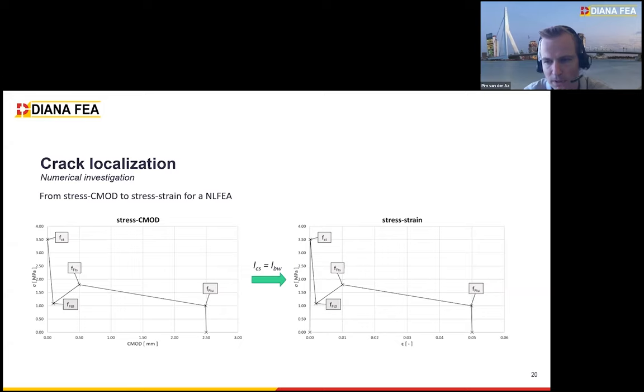And normally, as Professor De Prisco explained in the previous presentation, this is based on what your estimated crack spacing is. Your cracked zone, for example, that was the Y. However, this is for analytical models, and we are now looking at a finite element model. Because what you're actually doing in an analytical model is that you calculate the strain over a cross section, but then you still have to smear it out over a certain length, and that length is the characteristic length in order to get the crack width. So usually that's the crack spacing, or yeah, when there's only one crack, then that's the crack zone.